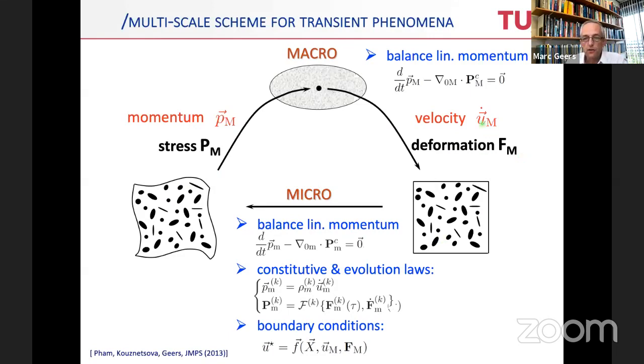It's actually the classical scheme, but in the downscaling relations, you also add the velocity from the macroscopic scale to the microscopic scale. And in the upscaling relations, you add the momentum. In the computational homogenization scheme, you naturally compute, by solving the initial boundary value problem at the microscale, what the constitutive coupling between those quantities is. So it's not present in any closed form, you just compute it. The machinery to do this is roughly similar to the classical machinery with which the other computational homogenization schemes have been developed. So I will not dwell further on this. I just want to show you that this is a method that can work.